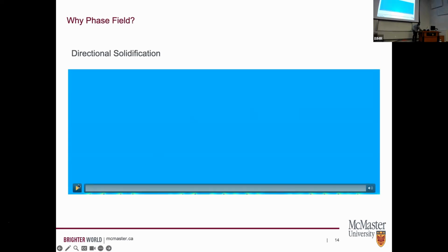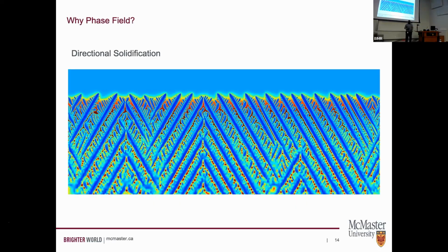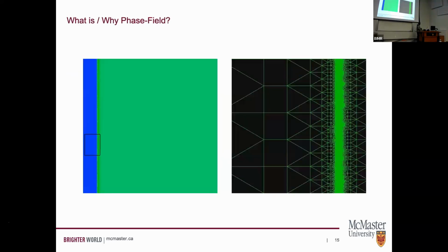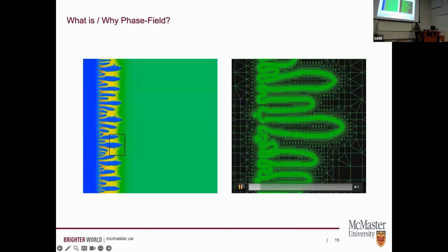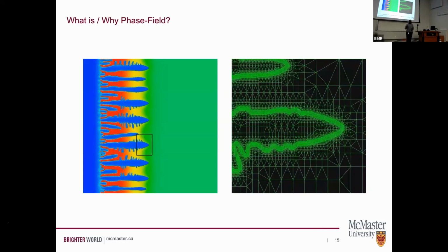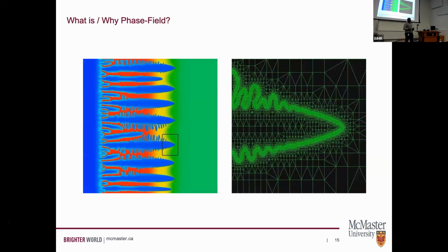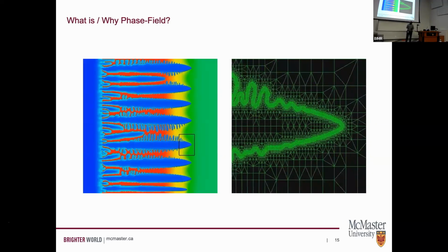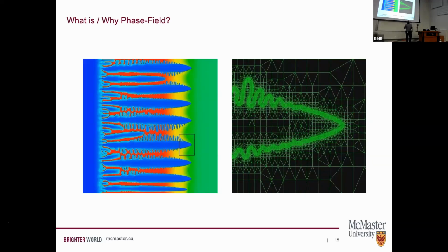So for a problem like dendritic solidification, where I have an extremely complicated microstructure, the tracking of such interfaces is not going to be ideal. And so then adaptive mesh techniques came along, and it turns out that you can track these interfaces as well, but still, if you have many of them, writing algorithms to do this is not trivial. And so can I write a model that will still get me this structure and the interface for free without having to worry about exactly where that interface is?